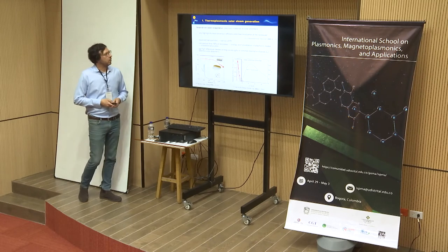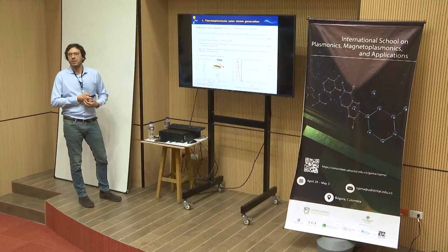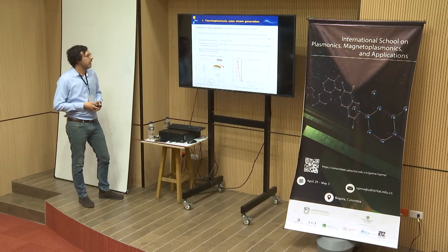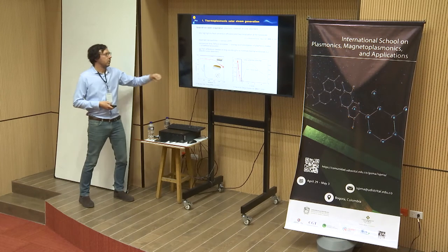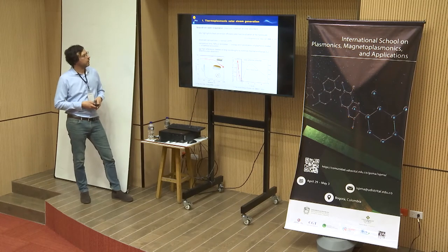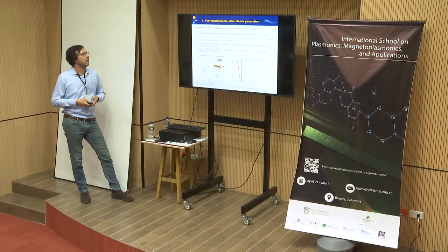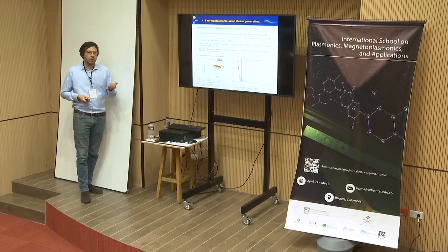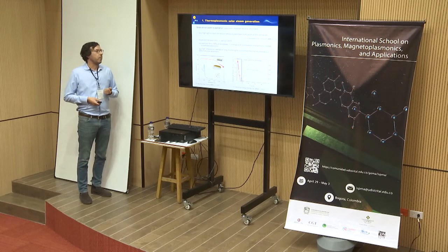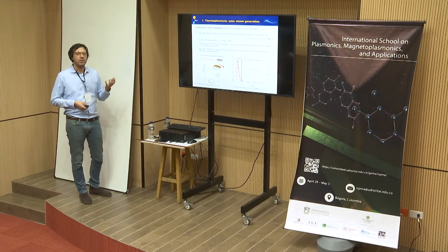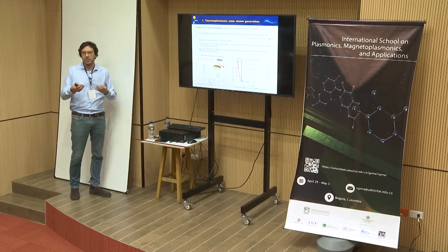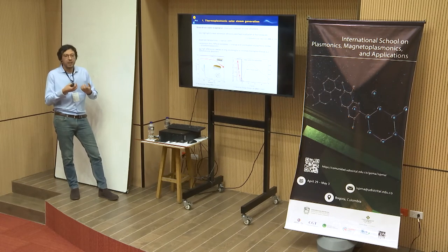And this is an example of plasmonic nanomaterials which have been developed for solar evaporation. In this case, the authors use a membrane of alumina, sputtered with gold nanoparticles by magnetron sputtering. If you take one single particle, it will have a single surface plasmon resonance, but in this case you have a collective oscillation of many different resonances because they interact with each other, being very close at the nanoscale.